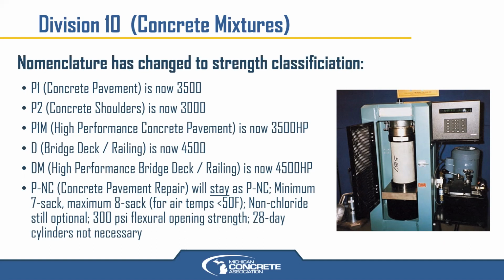So P1 and P1M both are 3,500. However, P1M being the high performance, a little difference in the optimized aggregates and things there requires that HP classification as well. If you just spec 3,500 for your pavement or your curb and gutter or whatever it is, you're just going to get the standard mix. If you specify an HP, then you'll get the optimized gradation and typically a special provision included in the proposal to specify the requirements of that high performance mix. So just note that strength plus optimized ag gradation for high performance. That's what the HP stands for, high performance.